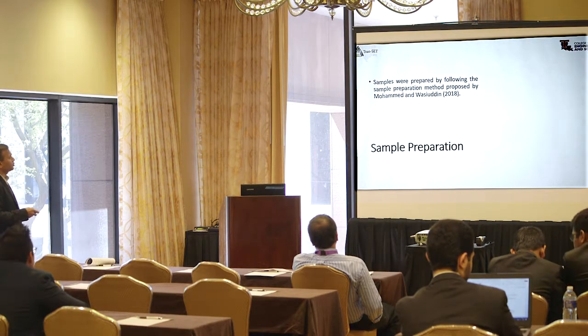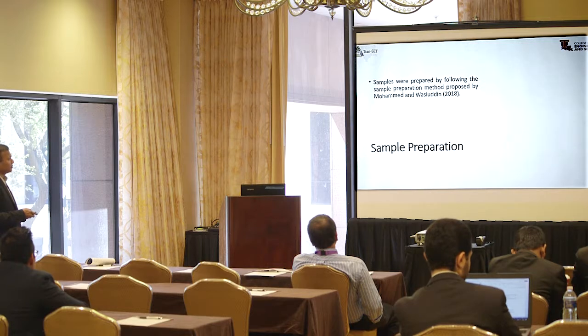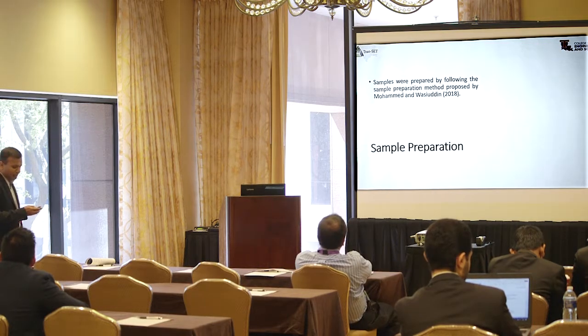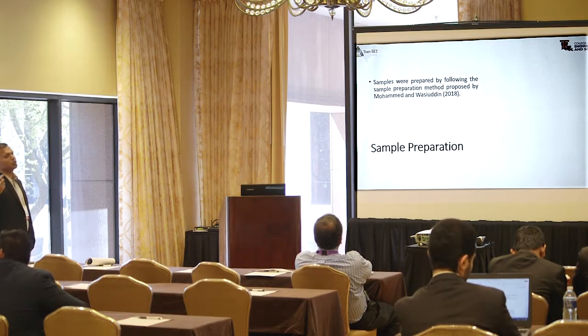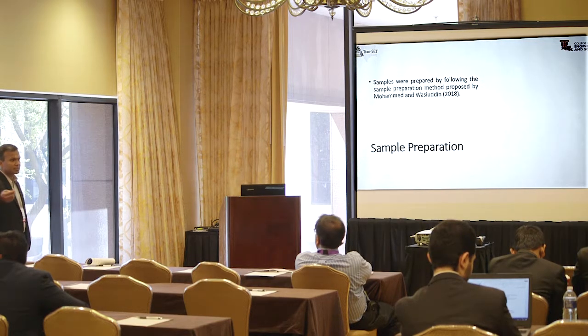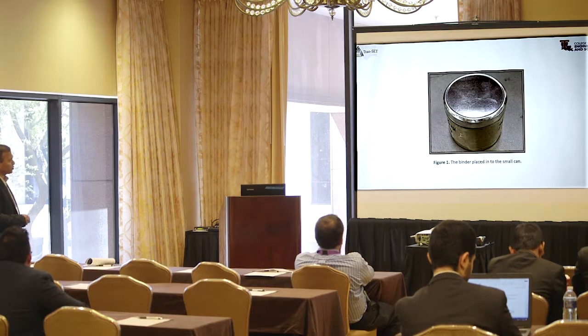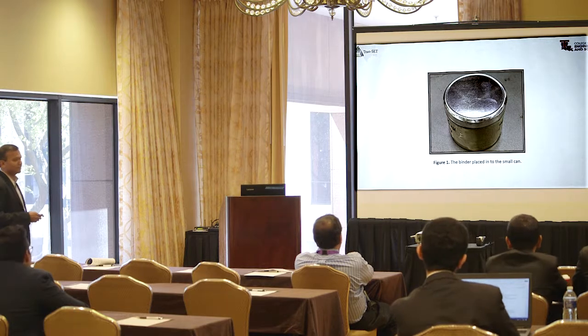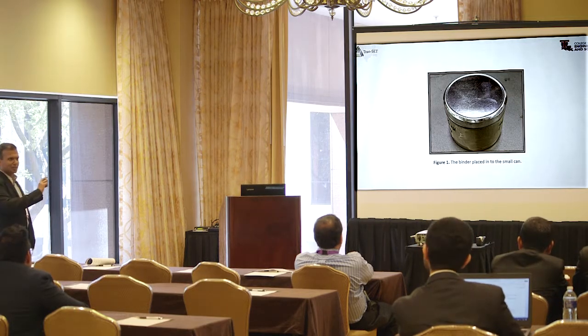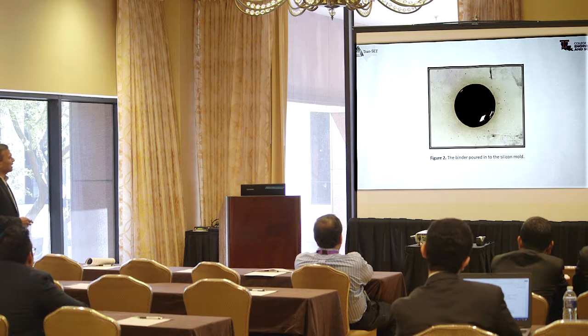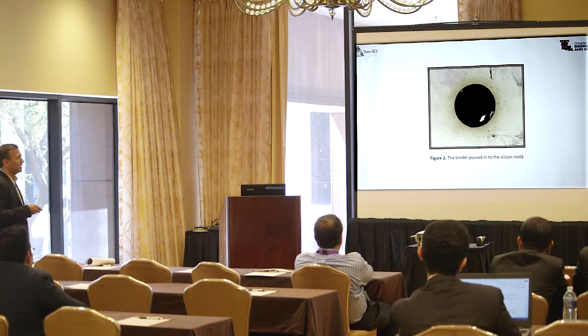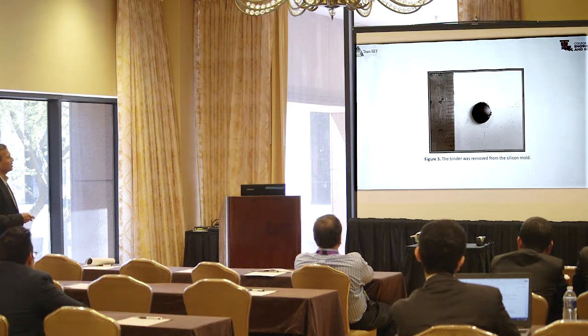So as you can see, we almost followed this previous method, and I'll show you. This is a description. I really want to show you the process that we followed, so I have lots of pictures. We started with placing the binder into the tin can, right? And then the binder was poured into the silicone mold. So this is the DSR silicone mold, so we know that one. And then you can measure this one. The binder was removed from the silicone mold, so this is the size.